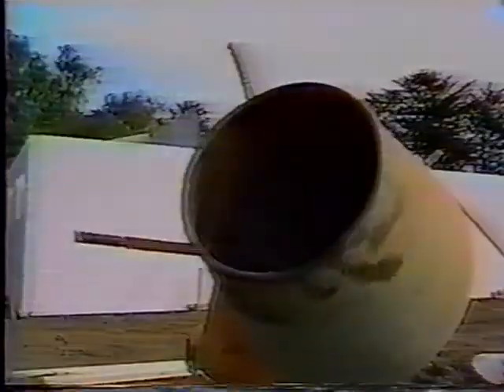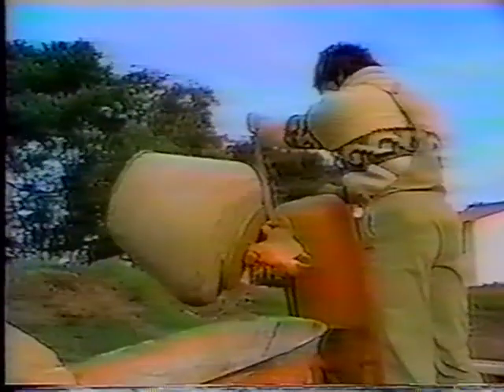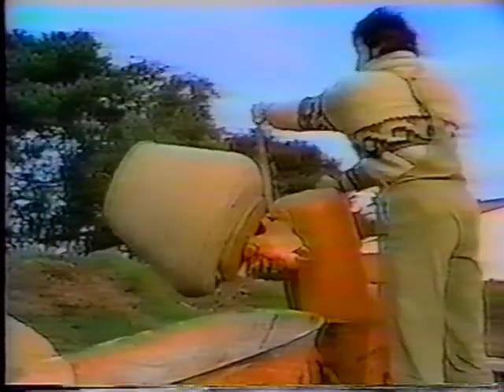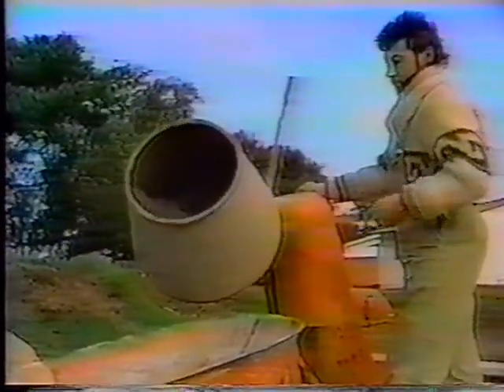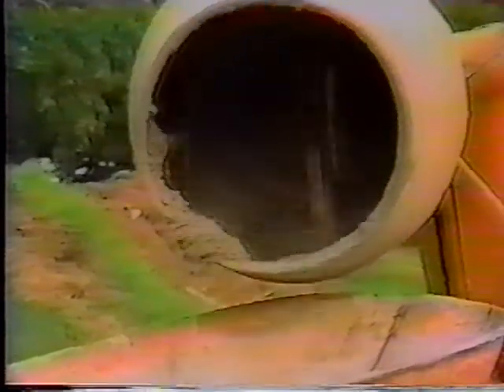The next step is to produce a mixture of slurry to put into the wall to enhance its strength, thermal values and dB reduction. We have a prescribed optimum fill, but this may vary from country to country, and if you are in an area where even the cost of the cement is beyond the budget, we have to consider that it may simply be a silica fill, sand or soil, or whatever is available locally. We would like the very minimum to be an admixture of soil, aggregate gravel, with a 10% minimum cement content.